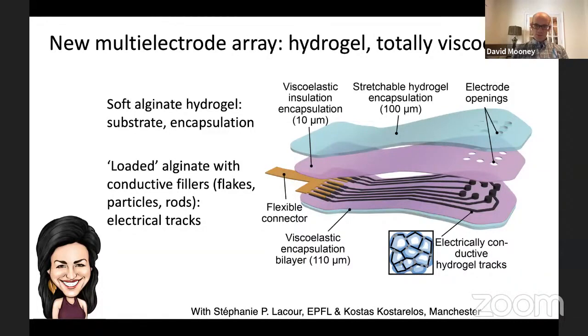based on hydrogels, would be totally viscoelastic to match precisely the mechanical properties of the underlying tissue. So the electrodes themselves would be viscoelastic, the encapsulation material would be viscoelastic, the whole thing would be viscoelastic, and we would exploit the ability of conductive fillers, things like conductive flakes and particles and rods, to provide the electrical tracks.